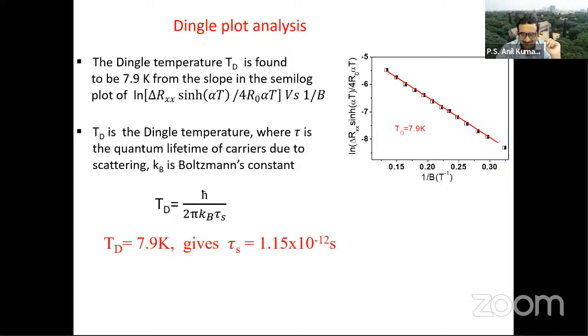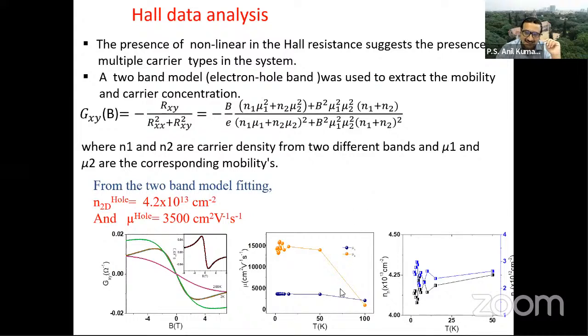Yes, I'm done already. So the last slide, I just wanted to give you very important information. If I look at the Hall data of this system, this crystal, 8% antimony doped bismuth selenide, you get a nonlinear Hall data, and this nonlinear Hall data can be fitted with two types of carriers. Now what we are getting is that if I look at the mobility of the charge carriers here, if you remember correctly, when I showed you the single crystal that had around 500 mobility, that has grown up to 15,000. There's a giant increase in the mobility of the system.